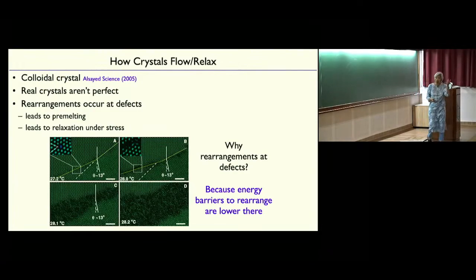This is just an illustration from my colleague Arjun Yodh at Penn of a colloidal crystal. Here it is far from the glass transition, and you see these grain boundaries in the crystal. As you bring it closer to the melting transition, where does it start getting disordered first? Where does it start having rearrangements first? It's at the grain boundaries. This is a blow up. It starts melting from the grain boundaries. And why is that? That's because the energy barriers are lower there.